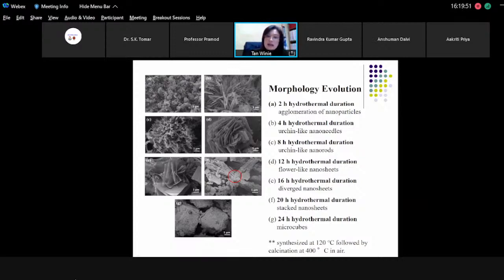You see that all these nanosheets are closely packed and interconnected, and you can see voids formed between them. However, at 16-hour duration, the nanosheets start to diverge. This is the 20-hour duration. At 24-hour hydrothermal duration, you can see microcubes start to form. So the morphology of iron cobalt oxide can be effectively controlled by just varying the hydrothermal duration.